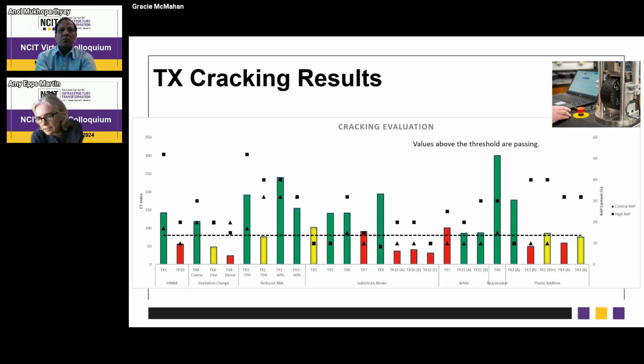So you can see a lot of different strategies have been applied here. And we want that performance to be at least as good as the control, which is yellow, or better than the control, which is green. Now you do see that there's, in some cases, the red bars mean that it's not as good as the control statistically at a 0.05 significance level.